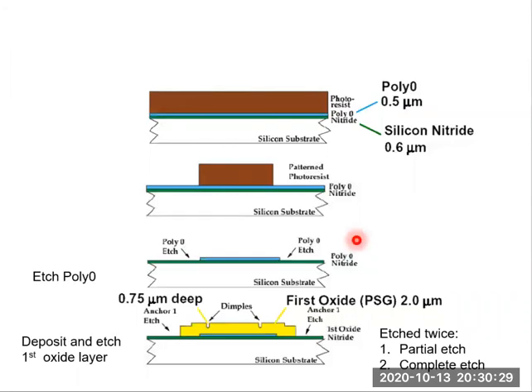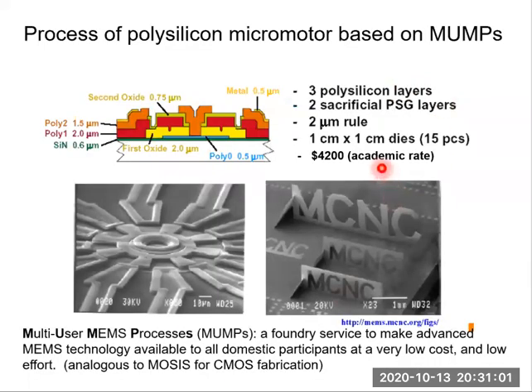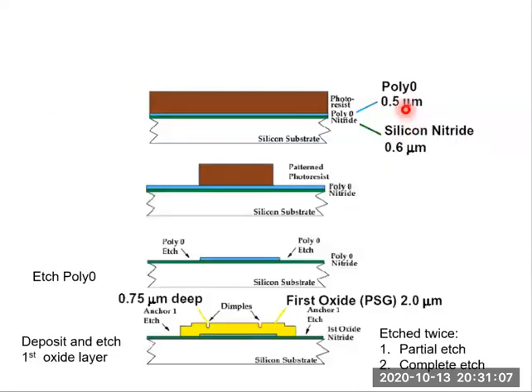Next, let's discuss the MEMS process of fabricating the polysilicon micromotor. First, deposit a 0.6 micron silicon nitride layer, then poly 0, 0.5 micron. Please note that poly 0 is actually the first polysilicon layer. As we just learned, there are 3 polysilicon layers. This poly 0 is the first polysilicon layer, which is 0.5 micron thick.